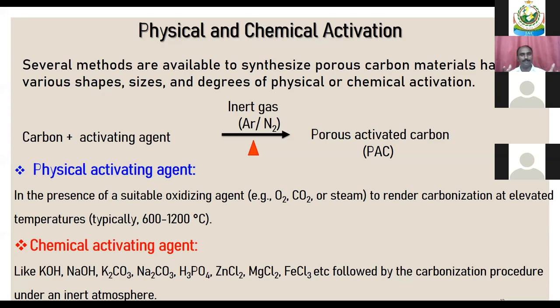And how to prepare the activated carbon? If you just burn the biomass, it will convert only to carbon. But we need high porosity, high surface area, and high pore volume. These properties are helpful for sensing, electrochemical storage, and energy storage applications. So, physical and chemical activation. There are several methods available to synthesize porous carbon materials having various shapes, sizes, and degrees of physical and chemical activation. What is meant by physical and chemical activation? Physical activation is in the presence of a suitable oxidizing agent like oxygen, carbon dioxide, or water steam, passed through a furnace tube at a higher temperature, typically from 600 to 1200 degrees centigrade, and we get the highly porous carbon.